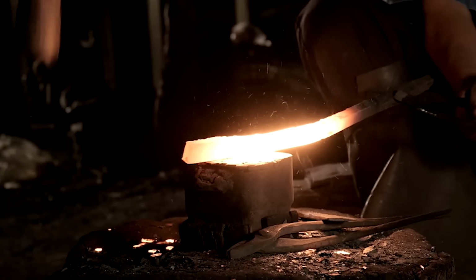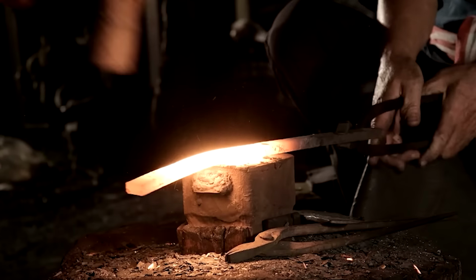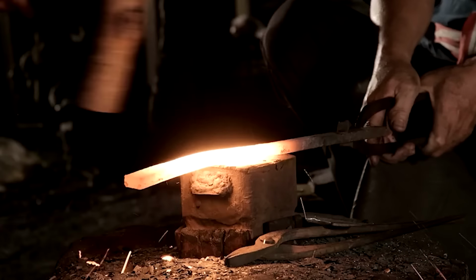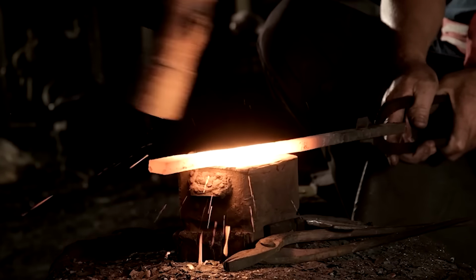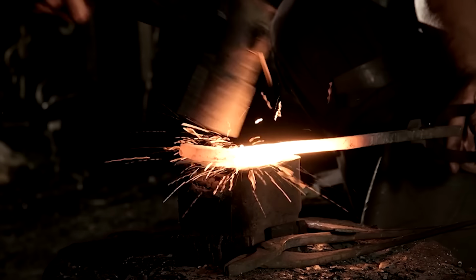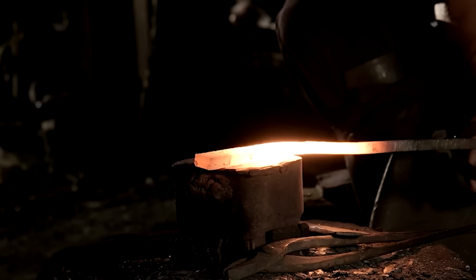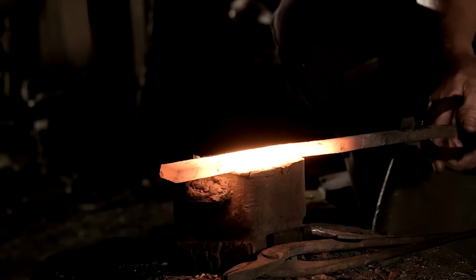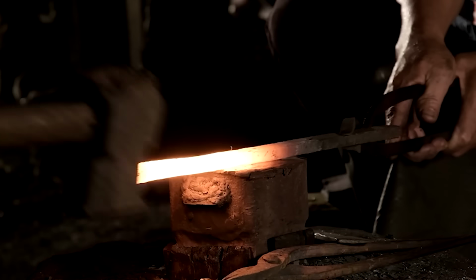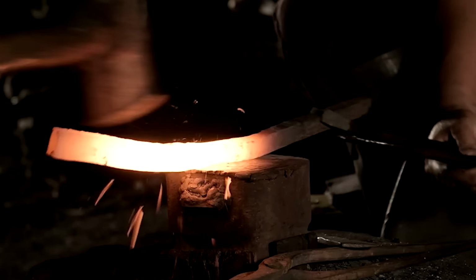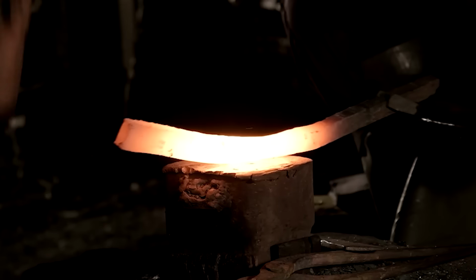Phase 2 was upsetting, covering strikes 81 through 160. Now the blacksmith rotates the iron 90 degrees. He begins striking from above, compressing the metal vertically. The iron thickens. The grains that were elongated in phase 1 are now forced to fracture transversely. This creates grain refinement in 2 dimensions.